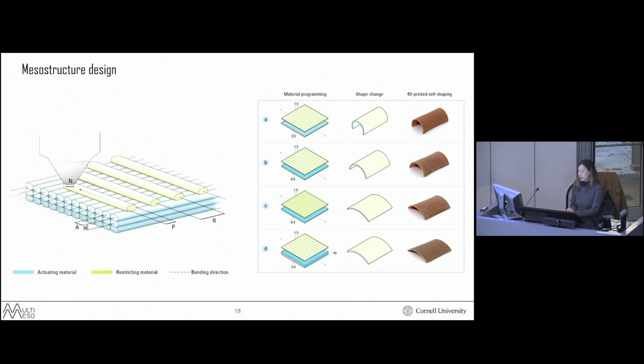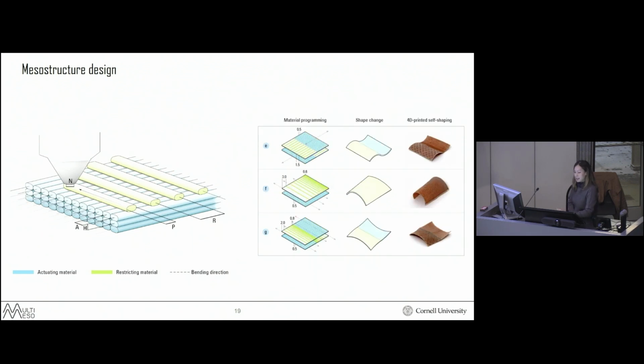So to develop the tools for 4D printing, my first steps were to explore this principle in a systematic way by programming the extrusion paths with different parameters, such as the spacing and the layer height between those paths. And with that, you can control the bending in different directions, the amount of bending, and even the speed of bending. And by combining and stacking together these different bilayer building blocks, as I call them, you can expand the geometric possibilities.